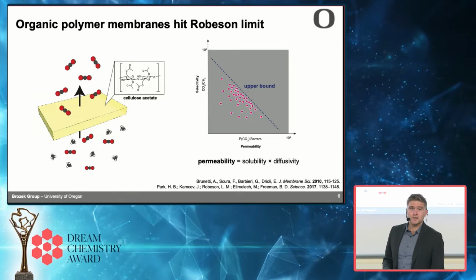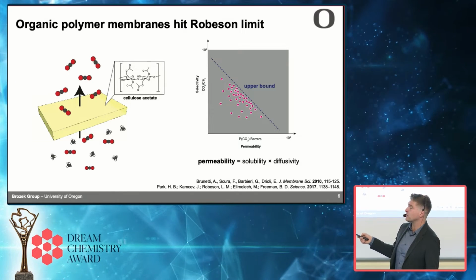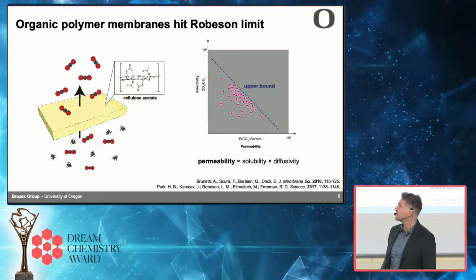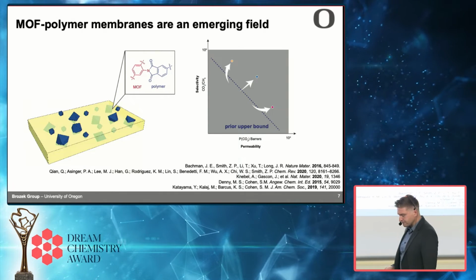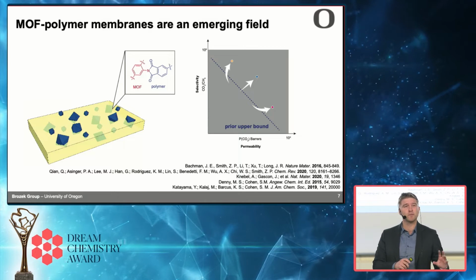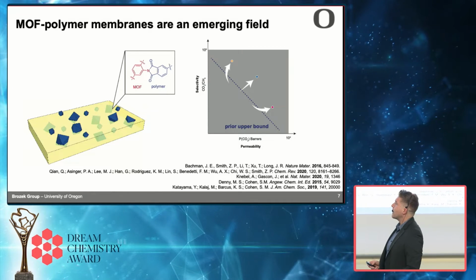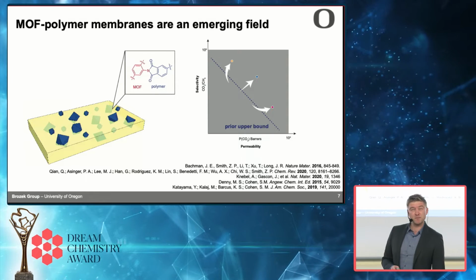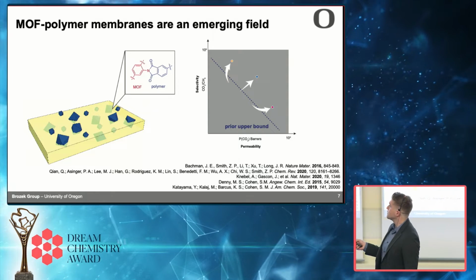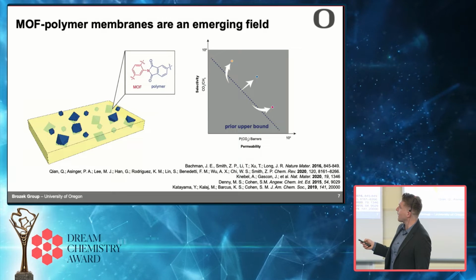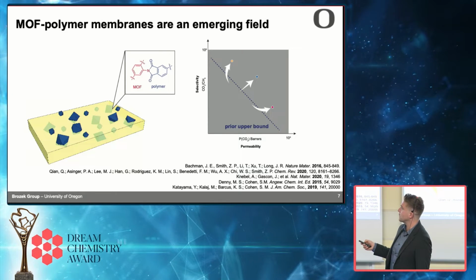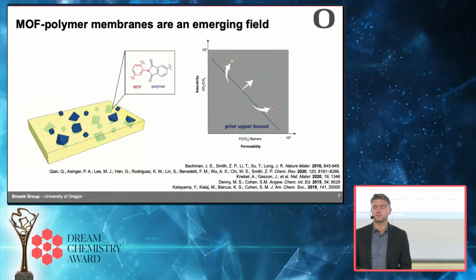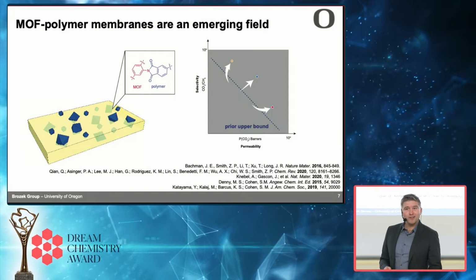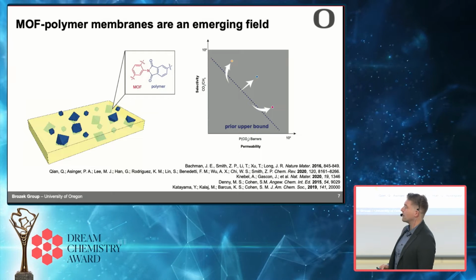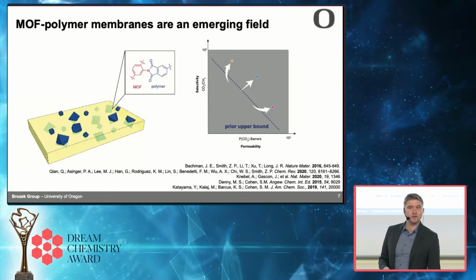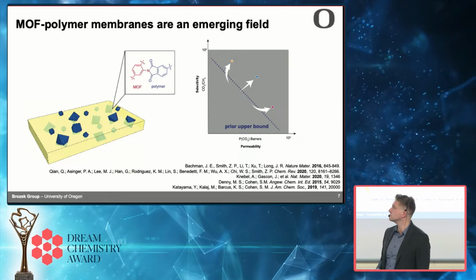And so there's a lot of interest in being able to improve this upper bound, to push the performance of membranes to better and better selectivity and permeability. For this reason, in the last 15 years or so, people have moved away from cellulose acetate-based membranes and have embraced this idea of a mixed matrix membrane. This is something that includes a MOF-based material that's either covalently attached to some polymer, that's the example I'm showing here, or they're simply mechanically mixed with each other. With that better chemical tunability of a MOF, people have found that you can push the performance beyond those original upper bounds that people identified 20 years ago.